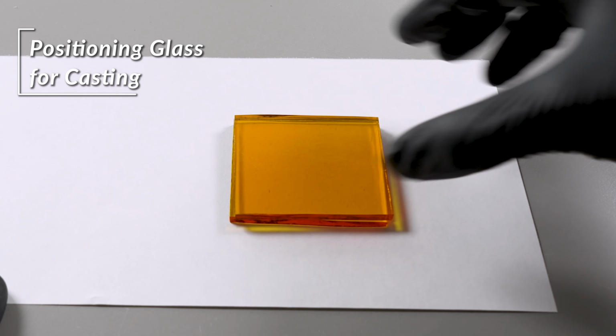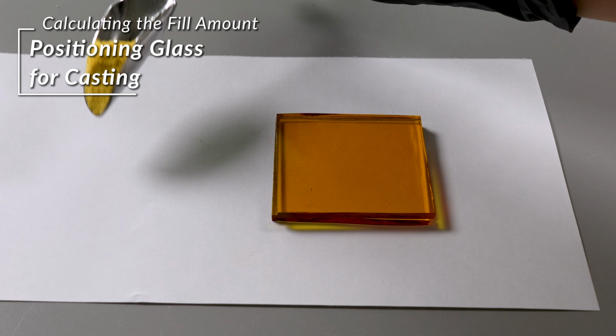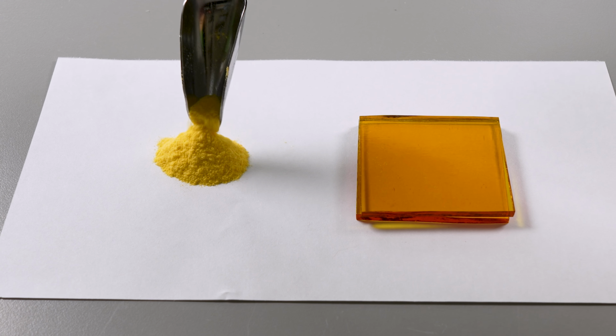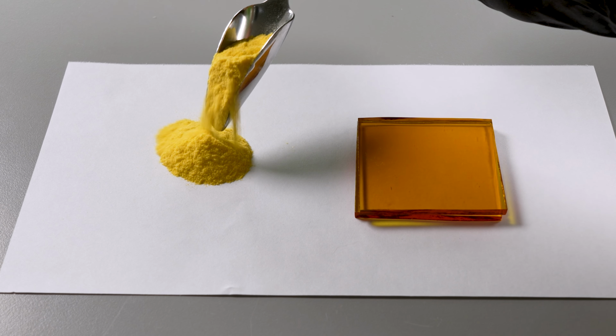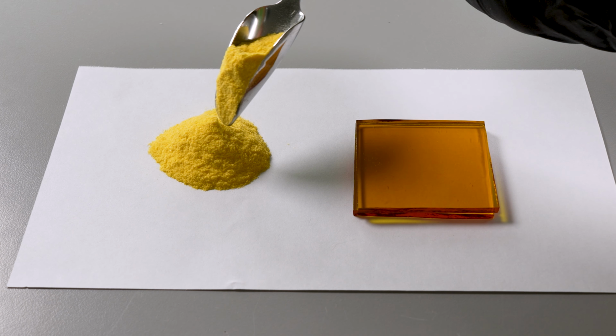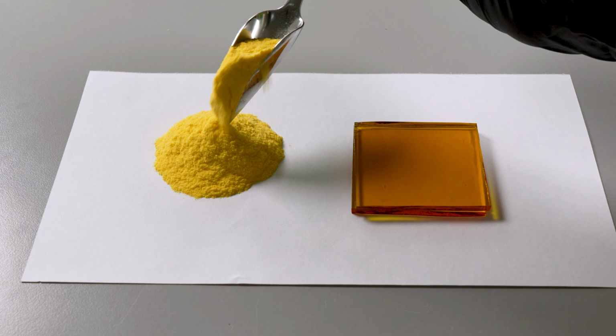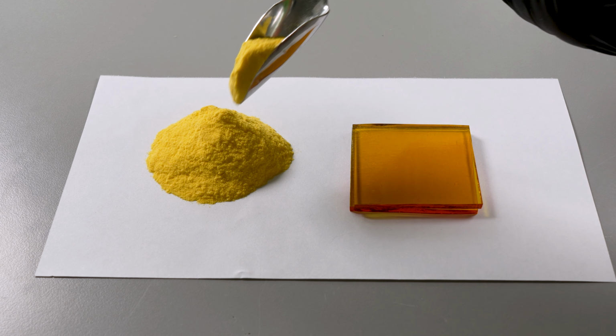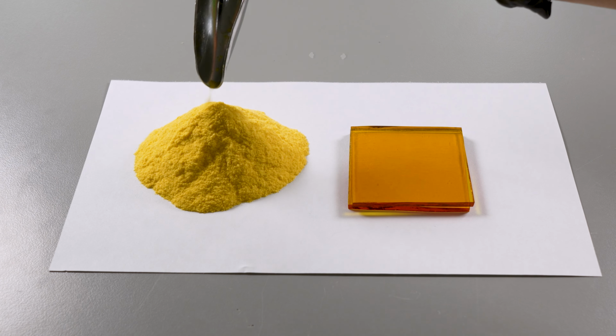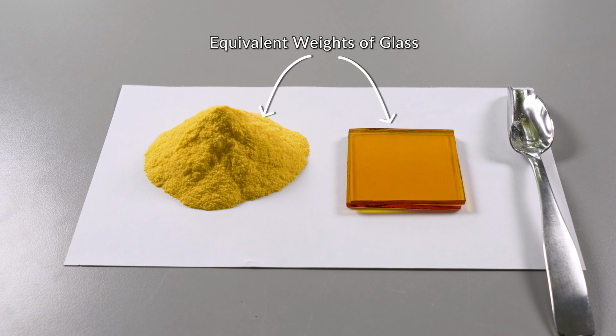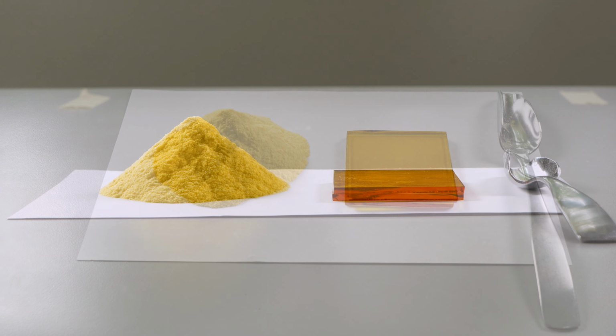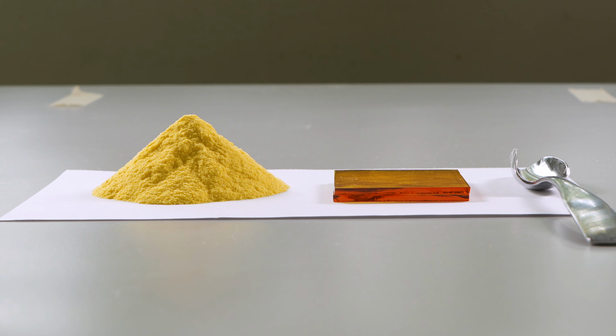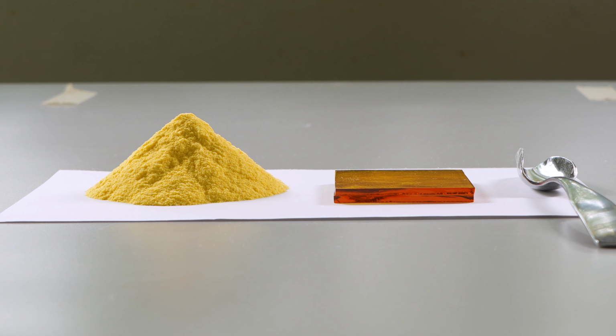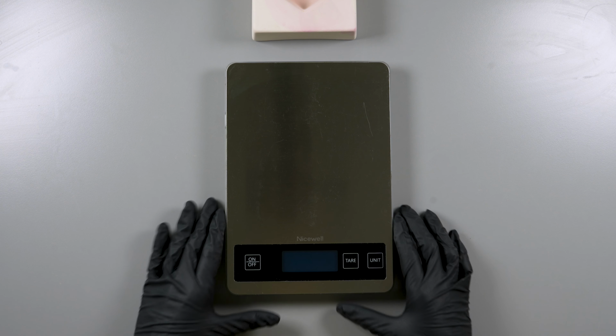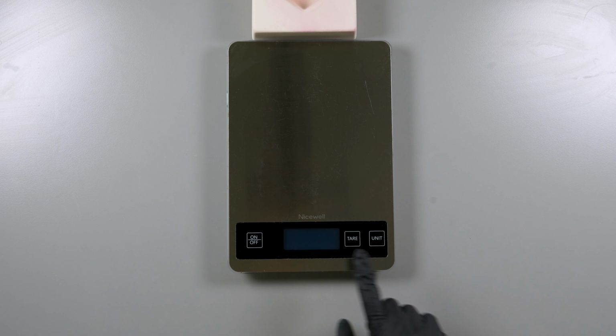In order for this glass to completely fill out a casting mold post-firing without shrinking significantly, the mold should be filled with an amount of frit equivalent to 2 layers of 3mm sheet glass, as per the 6mm rule we learned in Lesson 4. Because of this necessity, many casting molds will come with a recommended fill weight, allowing for the measuring and weighing of the exact amount of frit needed to fill it. But if you don't know the exact amount of frit required for a mold, you can calculate it yourself.